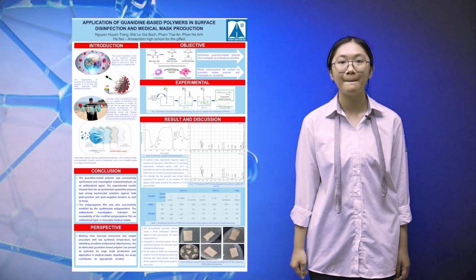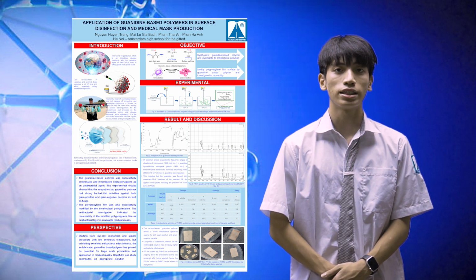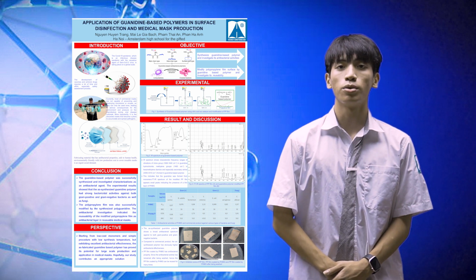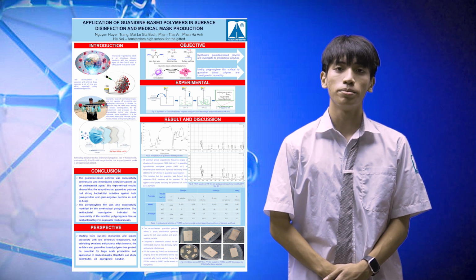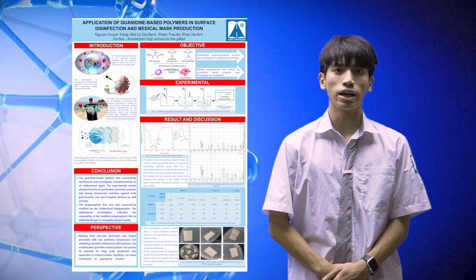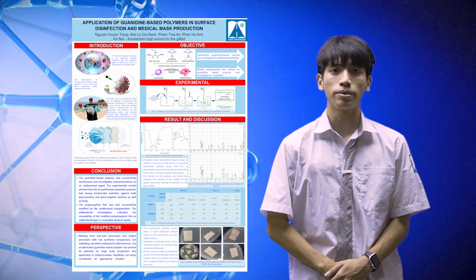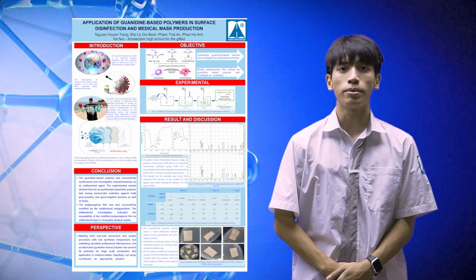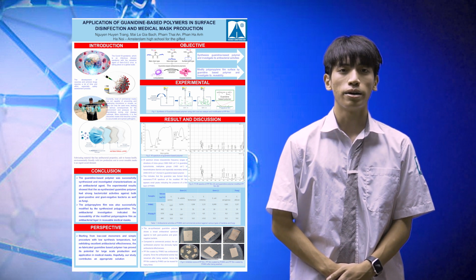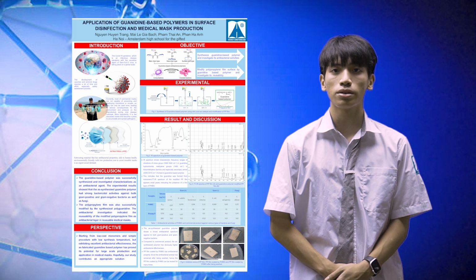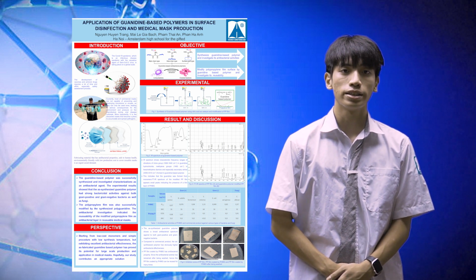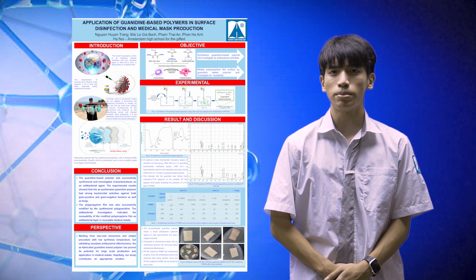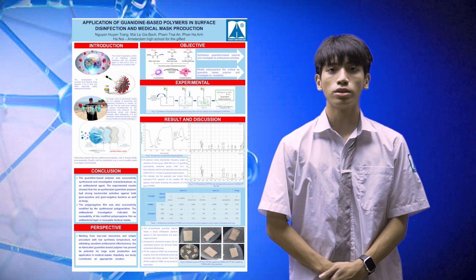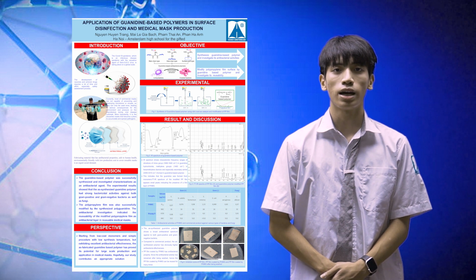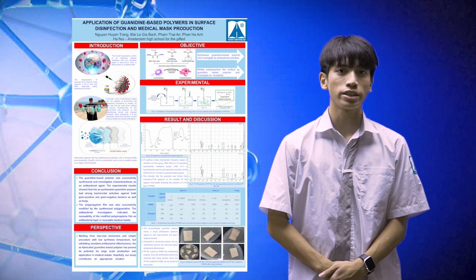We investigated the antibacterial activity against bacteria and fungi. The results are included in Table 1. The as-synthesized guanidine polymers show strong antibacterial activities against both gram-positive and gram-negative bacteria. IC50 and MIC values are smaller than 15 micrograms per milliliter and 32 micrograms per milliliter, respectively, indicating that PHMG has a broad antibacterial spectrum. Compared to the commercial product, the as-synthesized polymer has obviously higher antibacterial effectiveness.